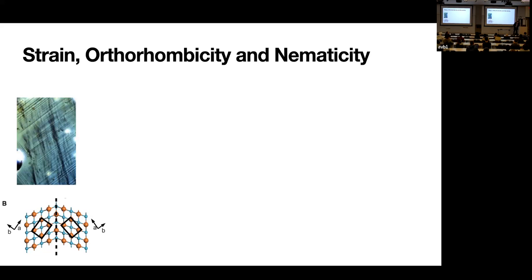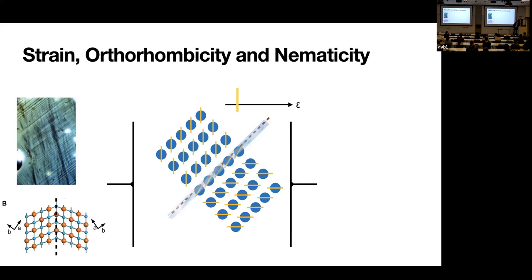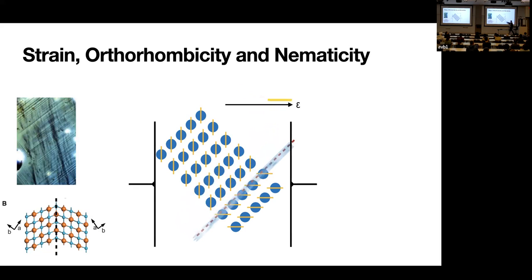Now you can bias the system to be in one kind of rectangle or another by a symmetry breaking field. But in this case, it's not a magnetic field like it would be in a ferromagnet. You have to use the broken symmetry of the system itself, like what direction the rectangle is. And in this case, the symmetry breaking field is simply strain. Just like the sheep going through the constriction, it's like squeezing the crystal in one direction. And so here's a cartoon of those same atoms, and if I squeeze them, say this is my picture of a vise, I can move that domain wall so then I can get dominant rectangles in one direction and not the other.